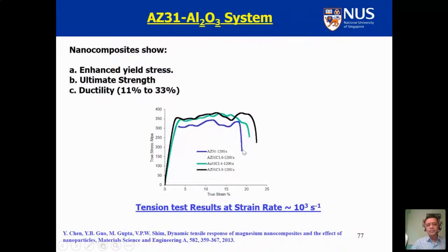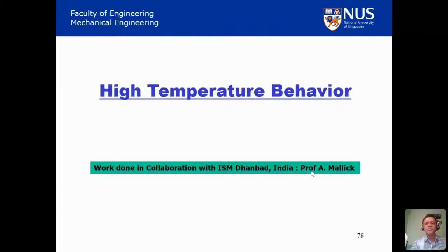Now, in this graph, you focus on the blue curve here and the black curve here. The black curve is the nanocomposite. The blue curve is a normal material. So you can see that the black curve shows higher strength and higher ductility when the strain rate is 10^3 per second. So under the collision, if you use a nanocomposite, your material suddenly becomes stronger. So the probability of survival for the passenger becomes higher. And this is what the transportation companies or automobile companies actively look for.